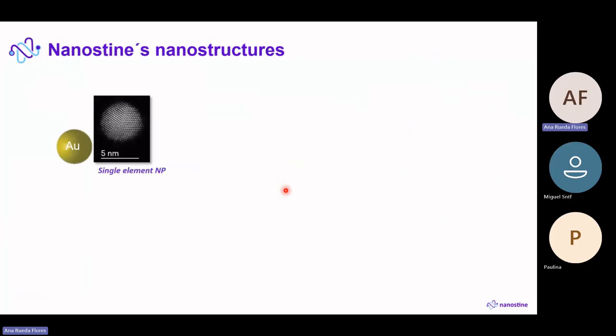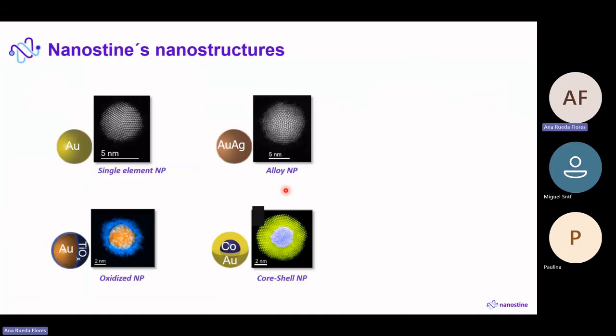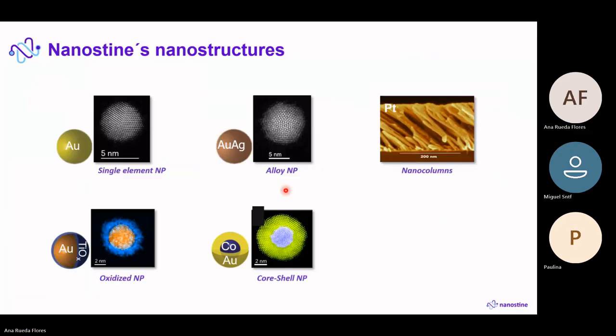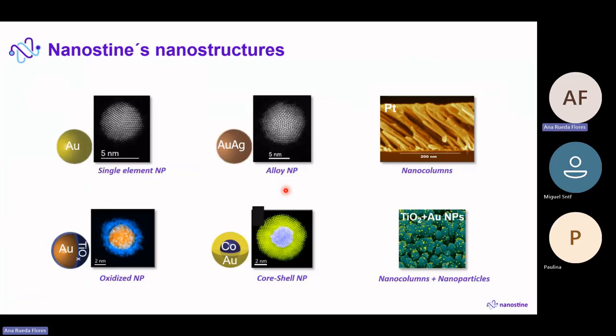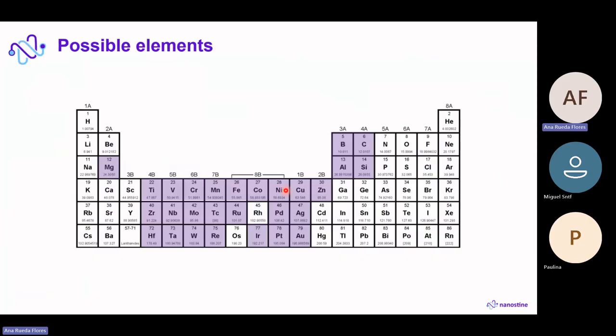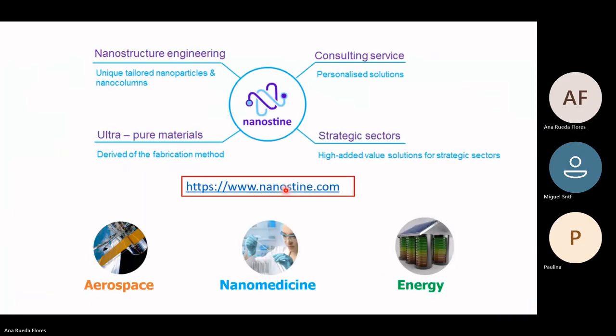And so what Nanostine can manufacture are single element nanoparticles, alloy nanoparticles, core shell nanoparticles, either with an oxide in the shell, or with another metal in the shell, nanocolumns, and nanocolumns decorated with nanoparticles. All these materials can be produced by Nanostine. The possible elements are here, stained in violet. So basically, all the elements that you can sputter with a DC current is what we can use in Nanostine. And the materials that Nanostine fabricates are important basically in three fields: for the aerospace industry, for nanomedicine, and for energy and environment.